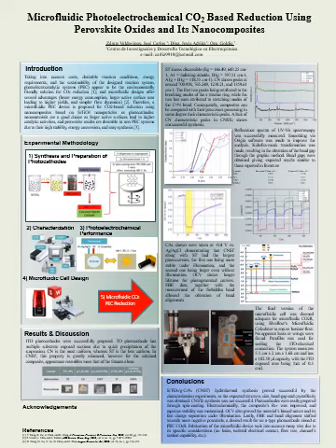After this, a variety of characterization methods follow, validating the synthesis and some of the characteristics of the nanocomposite, such as light absorption. In this poster, we're showing the Raman spectra of the precursors as well as of the calcined composites. Strontium titanate shows discernible peaks according to literature, which are shown in the spectra. Thus, naked eye comparison can be performed. And for the amorphous carbon nitride, there are also peaks which can be easily compared with the composite.